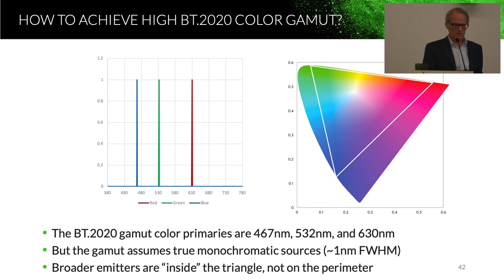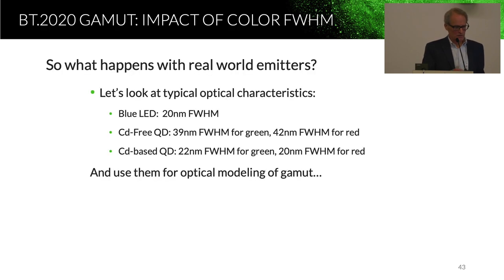So let's create a model. And here's the model that I'll use. I'm going to say that the blue LED is 20 nanometers, which is pretty much what it is. Cadmium-based quantum dots, I'm going to assume that the full width-half max, or breadth of that emission spectrum, for green is 22 and for red is 20. That's for the cadmium case. And for the cadmium-free case, I'm going to say it's 39 and 42 for green and red, respectively.